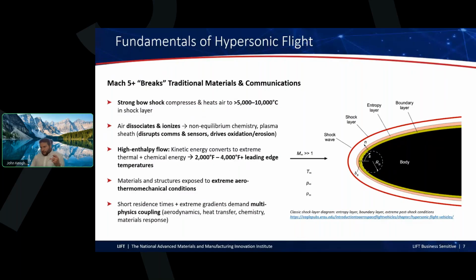Aerothermal heating and just the conditions in general begin to change dramatically once you hit Mach 5 and above. So looking at the graphic on the right, don't spend too much time looking at it, but the idea is that you have a very strong bow shock. And that bow shock not only compresses but also heats that air in the bow shock region anywhere from 5,000 to 10,000 degrees Celsius. Technically, those numbers were Kelvin, but 273.15 difference, no big deal.